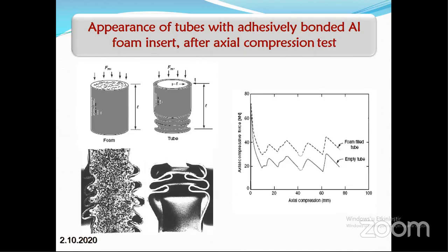This picture shows the appearance of tubes with adhesively bonded aluminum foam interiors after axial compressive test. This is the tube filled with metallic foam. This is the empty tube. When we applied compressive test on these materials, the shape is like this. And then the graph shows that this is the empty tube. This is the foam filled tube. So that's quite good compressive strength of the metallic foam.